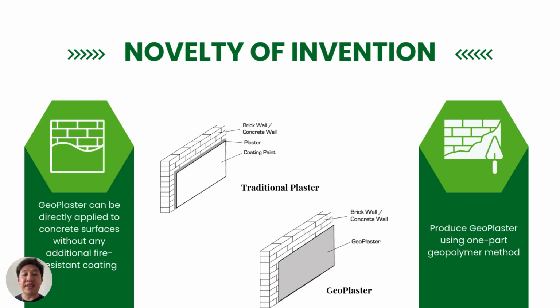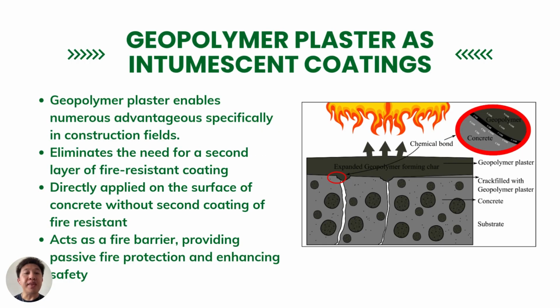So the novelty of this invention is that GeoPlaster can be applied directly on the concrete surface without any additional fire-resistant coating. As we can see, these are the differences between the traditional plaster and the geopolymer plaster. And GeoPlaster is very easy to use as it uses a one-part geopolymer method, which is just adding water, and it can be applied directly.